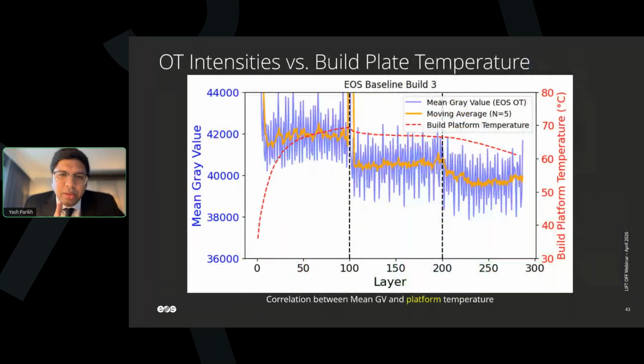That purple signature is the mean gray value based signature for all 142 samples run three different times, right? What I'm trying to say from this is that the mean value approach is not so preferable. We need to rely on something else in laser powder bed fusion. There is remelting happening for at least 5 to 10 layers, depending, of course, upon your layer thickness and what your laser power is.